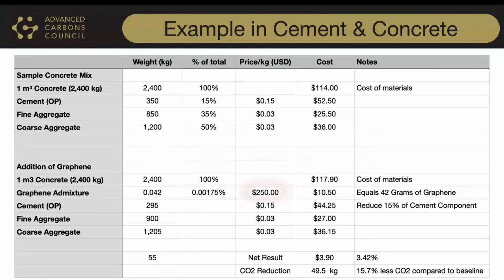And if you go to as high as $250 a kilo for the graphene component, at everything else being equal, you now come in at an additional cost of $3.90 per cubic meter. And the question would be, if you do have a low carbon concrete, if the ready mix company could add even just a 10% premium, you are still more profitable with this use of graphene, even if you're paying $250 a kilogram, given the load factors that we use. So there's an example in concrete and how this pencils out.